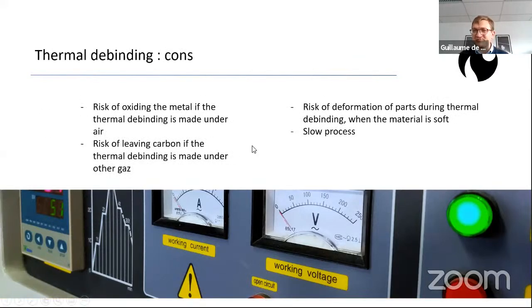What are the cons? Why doesn't everybody do that? Well, the first thing, which is very obvious, is that you have quite a big risk of having deformation during thermal debinding. So the way we remove the binder is by heating the part progressively so that the binder is going to be thermally decomposed. But of course, you're going to be at some point at a temperature where the material is relatively soft. This is how you printed the material, so of course, it is soft around 200 degrees Celsius. And so you need to find the right thermal cycle so that the part will get hard and have decomposed sufficiently before it is too soft. And that's really a very tricky thing to do. So that does pose some difficulty. It's a bit more complex to implement.